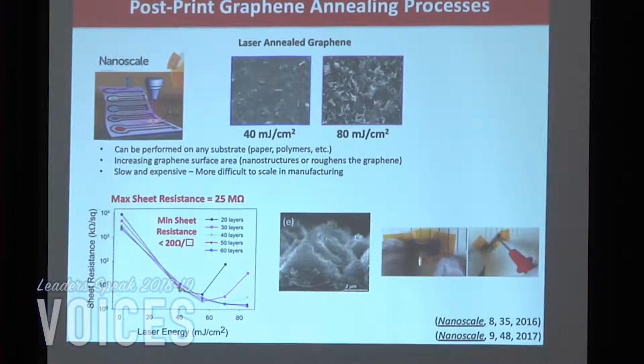So what we came up with is this rapid pulse laser technique. It doesn't harm the underlying paper or polymer substrate, but it anneals that top layer of graphene enough so that it carbonizes that ethyl cellulose, makes it conductive, burns off any remaining solvents, and then it can also nanostructure that surface a bit, kind of roughen it up, so to speak. So that's relatively flat with a low laser energy, but then these particles kind of stick up and start getting etched into a bit as we increase that laser power.